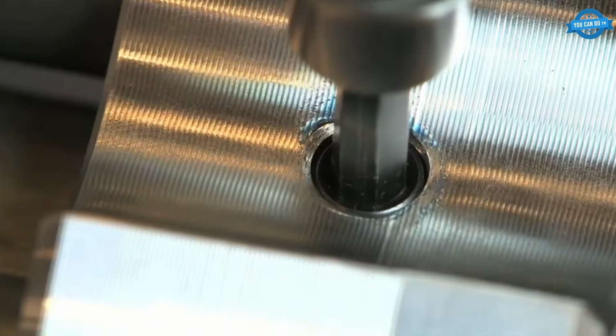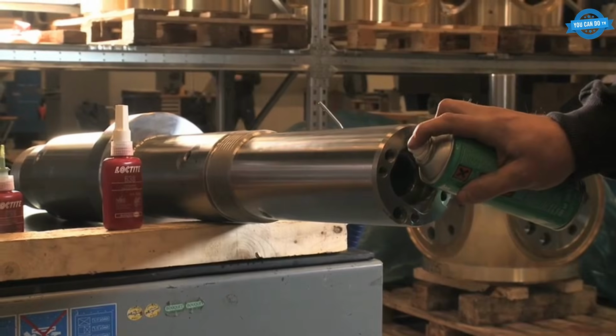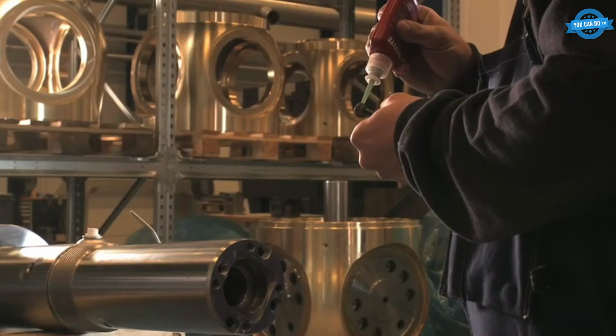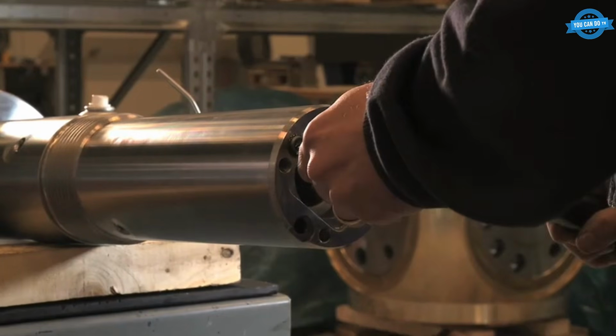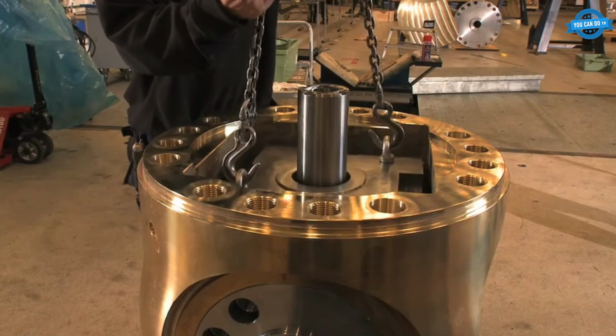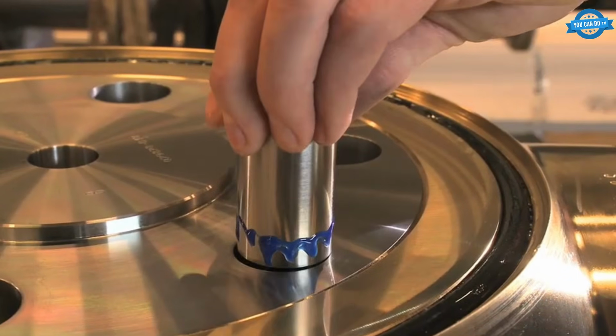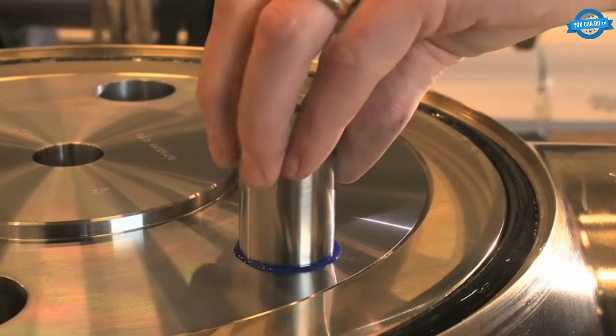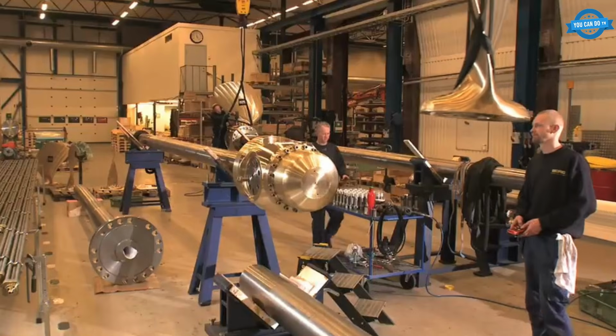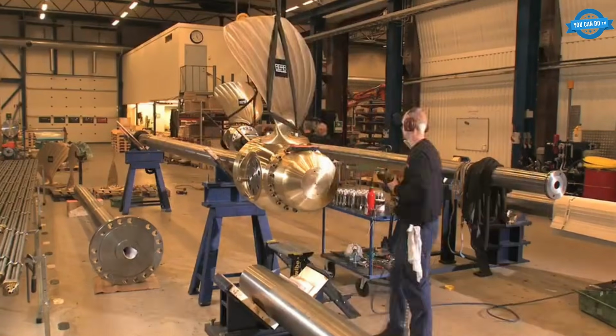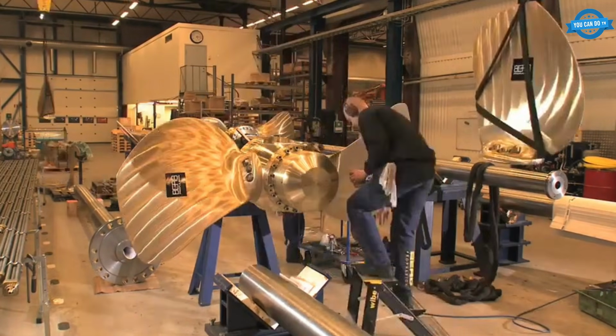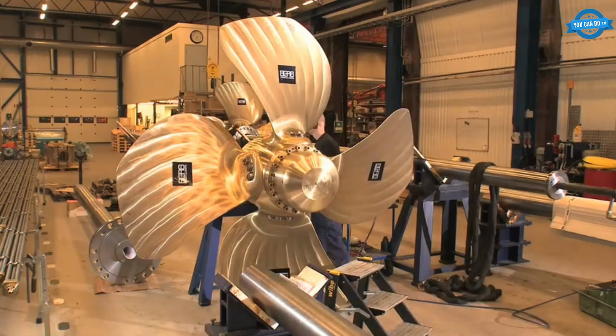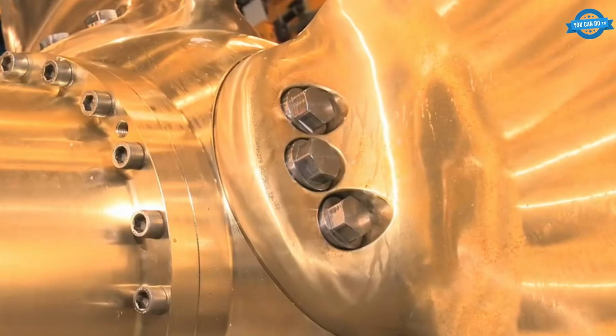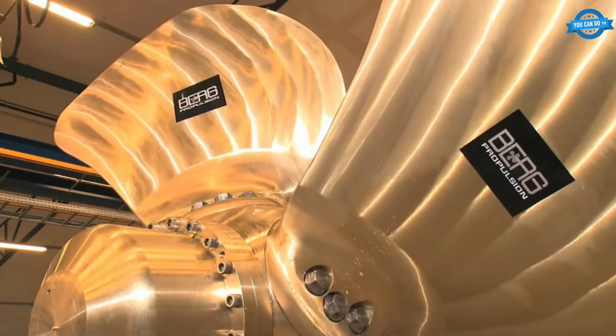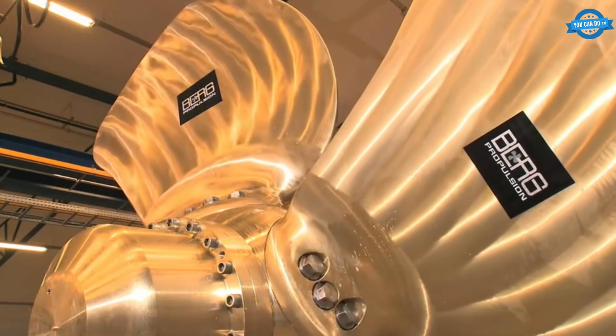The propeller hub is engineered to minimum tolerances, and especially hardened metal is worked on numerically controlled machines to reach the precision and finish that let the parts assemble perfectly. The completed unit is then proof tested at 70 atmospheres of oil pressure, around 2.5 times the actual service load it will see at sea, and that severe test is run just 1 hour after assembly.